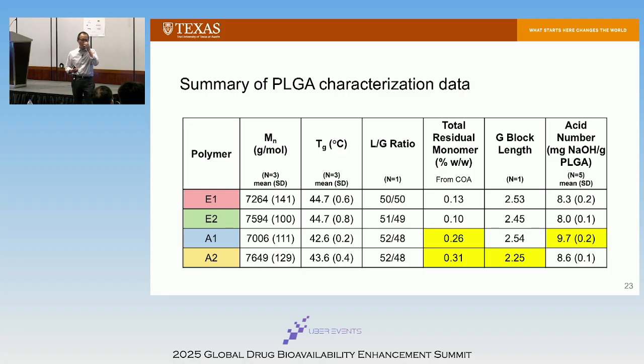Okay. As a matter of fact, one thing I did not explain to you, why we have those pores, right? Those implants have pores. For the extrusion, I used to do ASTs, and the material we got, we never had pores. Those pores are just because of air entrapment. Because we use a hot melt extruder, we actually don't really vent. There's no vent system. So when the air gets trapped in, PLGA has a very low Tg, those pores stay.